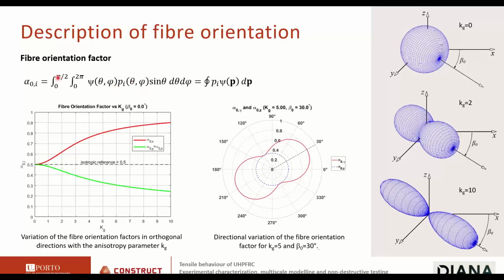So, well, the equation is not simple, but the results are very interesting to analyze. So what does this plot here at the left tell us? With Kg equal to 0, we have an isotropic distribution of the fibers. So we see that the fiber orientation factor takes the value 0.5, no matter the direction of your crack. Okay, the red line corresponds to the fiber orientation factor of a surface normal to the axis X, and the green curve to the perpendicular surfaces.